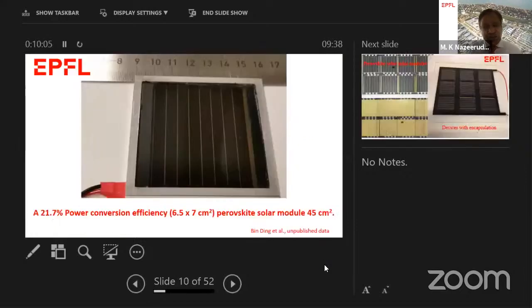So this shows you the scaling factor. Here we have a 6.5 by 7 centimeters mini module, and this mini module gives a power conversion efficiency of 21.7%. So the scaling factor has a small difference in the power conversion efficiency, which is negligible compared to silicon solar cells. In any case, we have the mini modules, and you can assemble these mini modules into a 3x3 or 4x4, depending on our requirements.